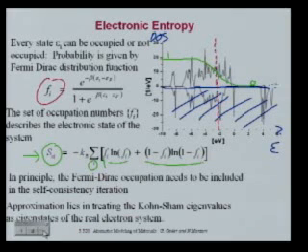It's just that in reasonable materials, metals and semiconductors, they look very much like one electron eigenstates, and this stuff works. Where it breaks down is typically in materials with very high degrees of correlation, transition metal oxides, where these things don't look at all like one electron eigenstates. Because what happens in those is, as soon as you do an electron excitation, the whole underlying eigenvalue spectrum changes.